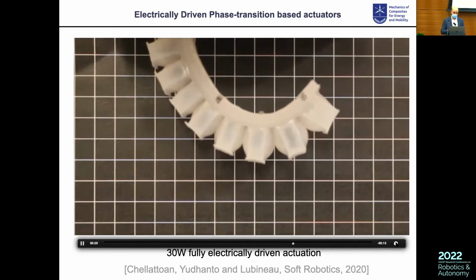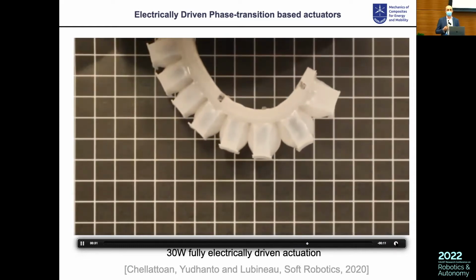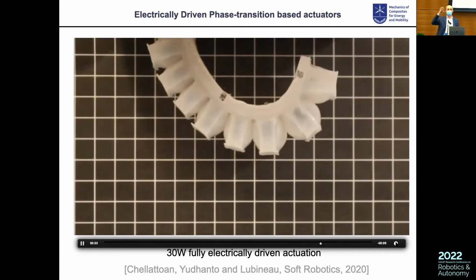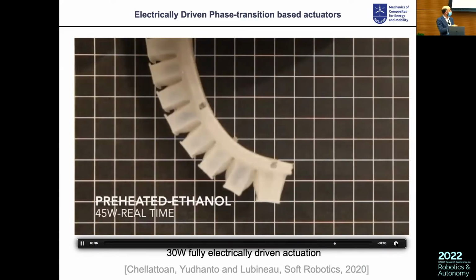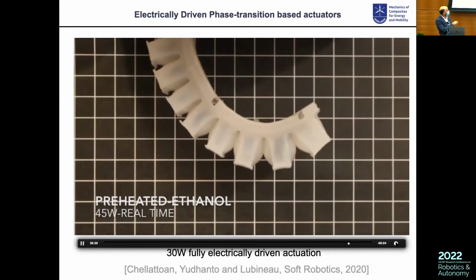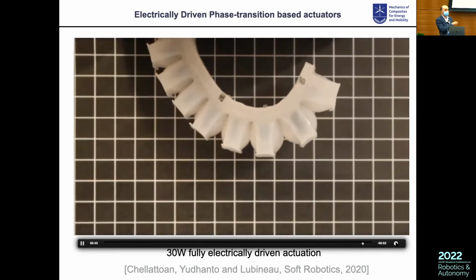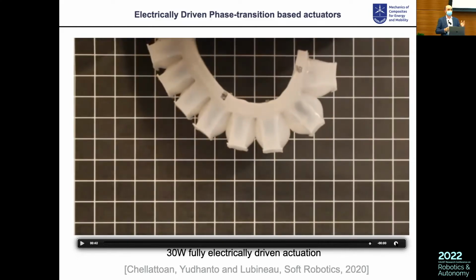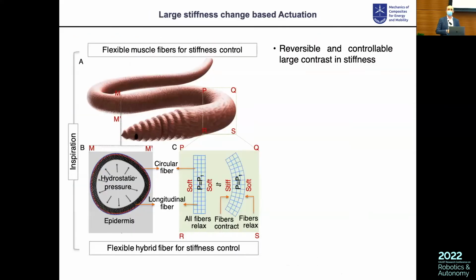And then, when you look at this, the shape of this motion is 100% guided by the stiffness of the membrane that you put around this. Here you get a bending in this direction because here you have a stiff membrane and here you have a soft membrane. So, of course, you are going to get a bending if you pressurize this. The second part of this project was about being able to control and have reversible actuation.